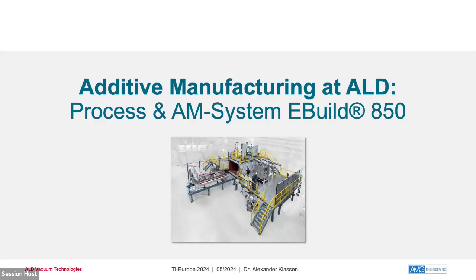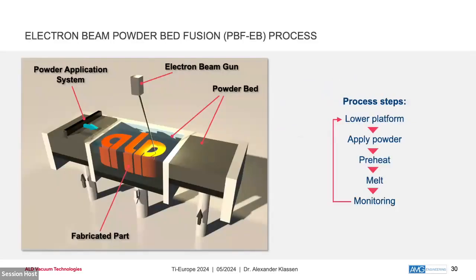And the steps involved are powder application, then heating up the powder to a certain temperature, depending on the material at hand. We are usually in the range between 600, 700 degrees C operation temperature up to 1,200 degrees for titanium aluminides.